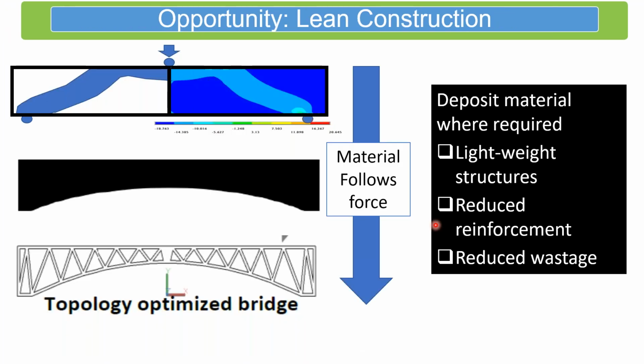So just to give you an example, suppose I take a beam and I apply a load on this. We know that typically we'll have a compressive strut that forms here, and then we provide a tension tie. Of course, a very simple example here. Now, what I can do here is start playing with this form and look to deposit concrete along here in an arch-like fashion, and then provide a tension tie. And using this concept, actually, we developed a topology optimized bridge where the shape has been optimized to provide the force flow such that this beam can now be represented using this arch type shape with these tie elements. And I can print this. In fact, we have printed this bridge at IIT Hyderabad. And this gives me an almost similar performance as the solid beam of concrete.